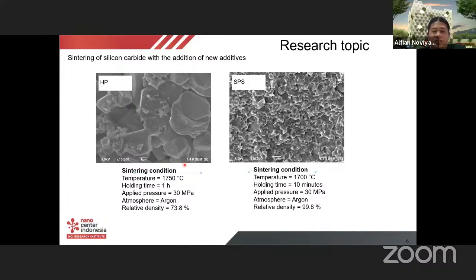And the density is very remarkable. So we can reach almost near the theoretical density, 99.8%, compared to 73.8% in the hot pressing furnace.